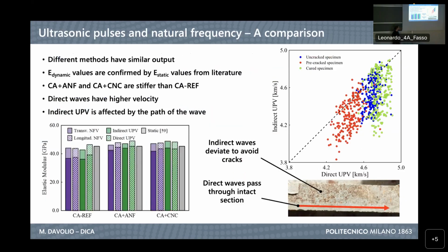Then I will just propose some comments on the different methods we use to address some properties. In this case, we have the elastic modulus. As you can see, most of the measurements are really close to each other. And also, they confirm the observation from mechanical testing present in literature. This means that as a practitioner, if I want to apply one of the methodologies and I'm not able to decide which one, any of them can be suitable to address the evolution of the performances because they are in good agreement with each other.